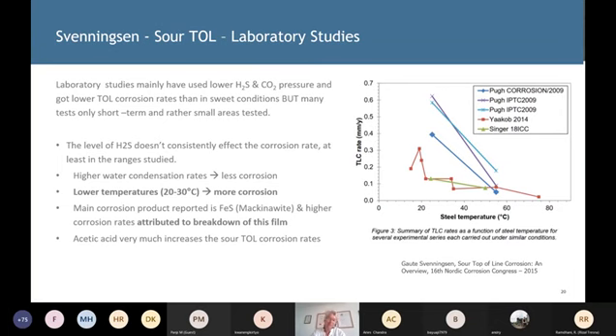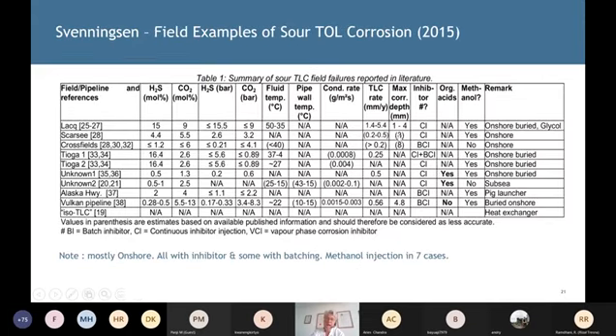And there's some impact of acetic acid, which is presumably affecting the pH. So there are some strange effects here, but just look at the kind of top line corrosion rates we're getting. These are quite serious corrosion rates, you know, plus or minus 0.4 millimeters. And he also publishes this data table, and these are the top of the line corrosion rates highlighted here, and you see that in the field we are seeing corrosion rates like this.